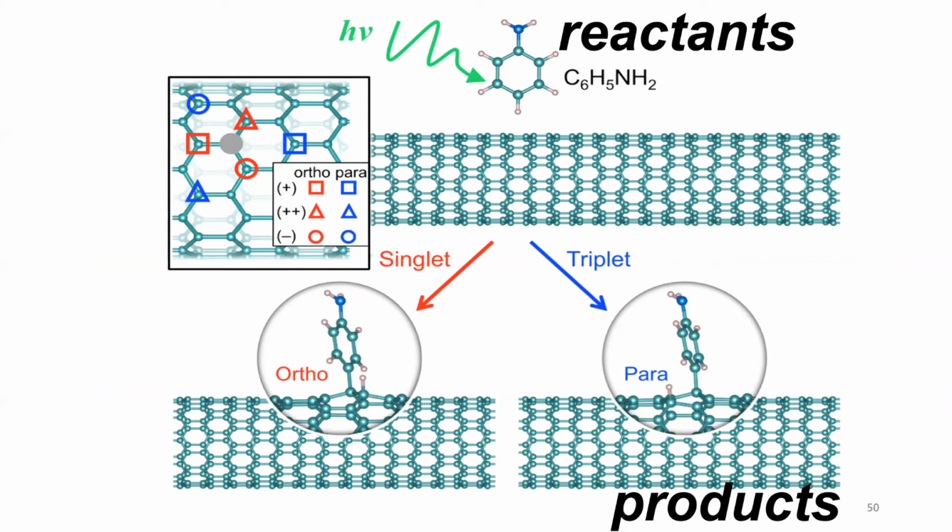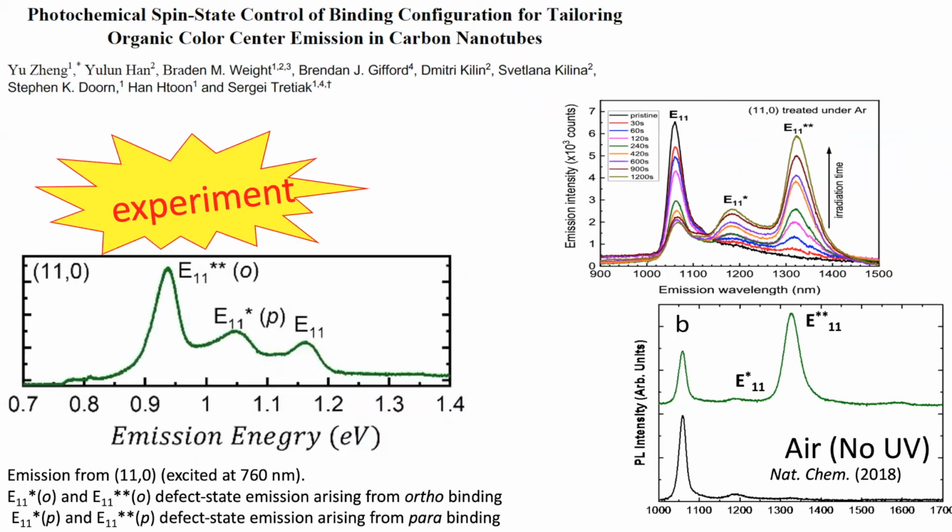By setting covalent adducts on such materials, there is a way to enhance their photoluminescence, and there is hope to get this photoluminescence with the right properties of photons, as single photon emitters. But the main challenge is that by synthesis, which is light-assisted, there is a distribution of several defects, each of which provides emission at different frequencies. So one needs to set up a selectivity.